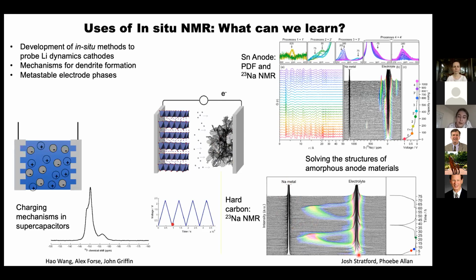And so just by doing one relatively simple experiment, you can watch the sodium move and become more metallic. And you can correlate that to, for example, the internal porosity inside these hard carbons, and you can corroborate that with, for example, SAXS measurements.